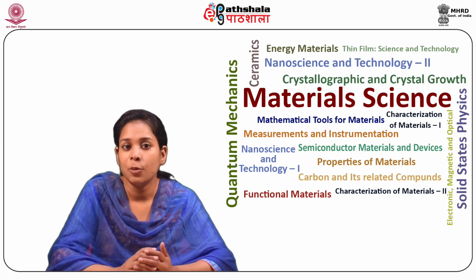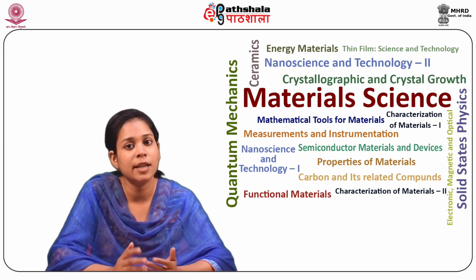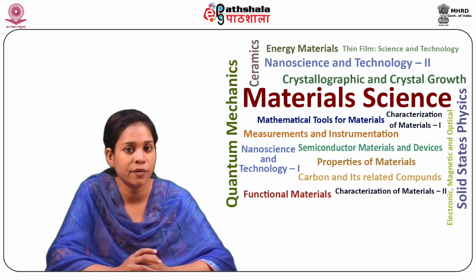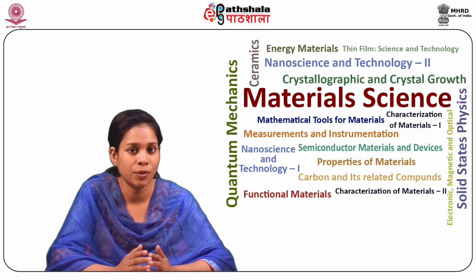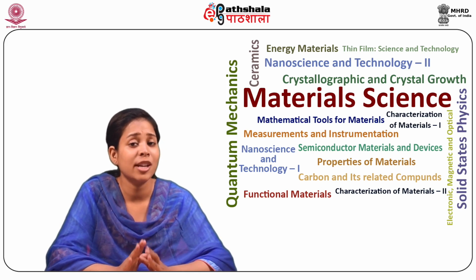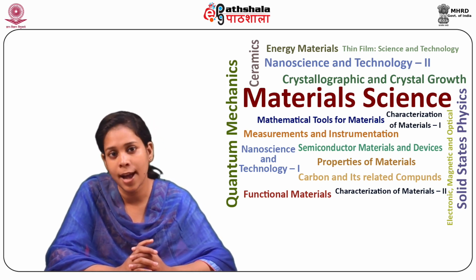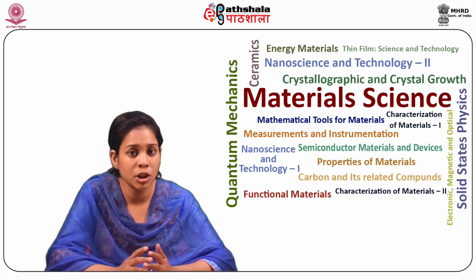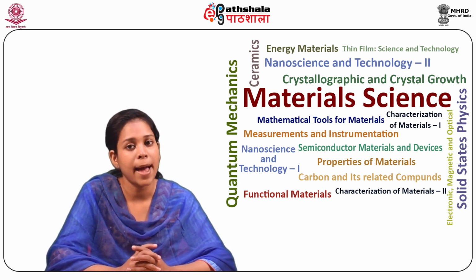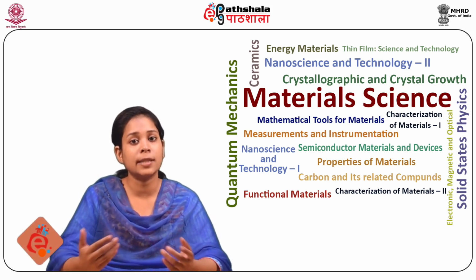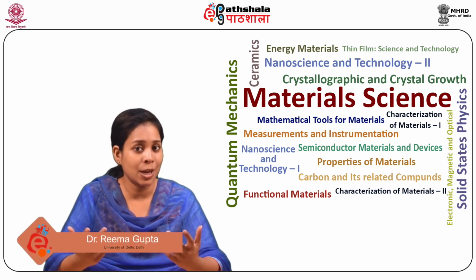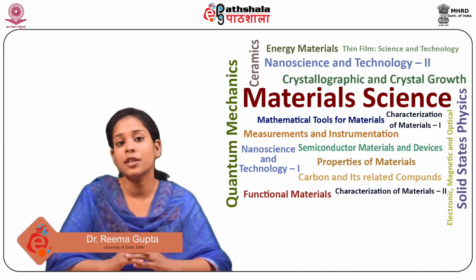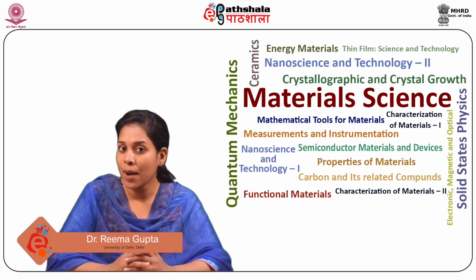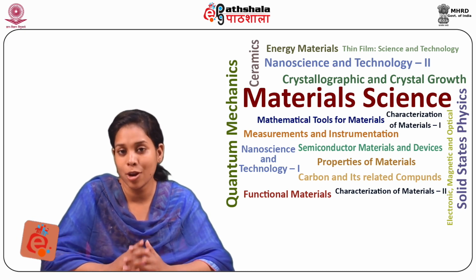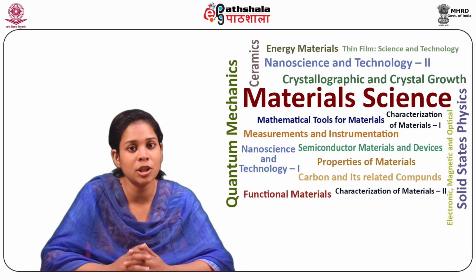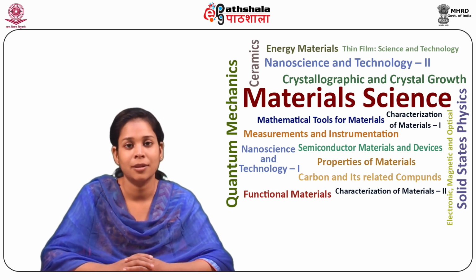In this case, aluminium replaces some of the silicon ions in the network of glass, as Al2O3 contributes only 1.5 oxygen per network ion, and some of the non-bridging oxygens are used up and converted into bridging oxygens. The effect of alumina is to increase the viscosity of glass, thereby increasing the elastic modulus and decreasing the coefficient of thermal expansion. Thank you.